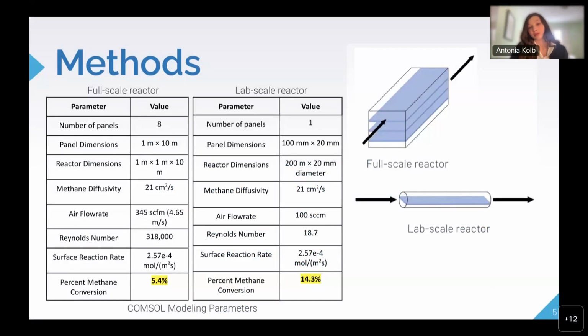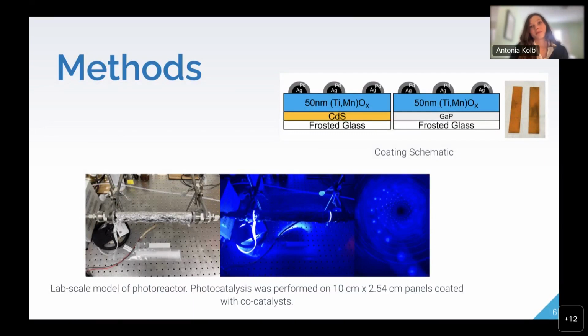This reactor would be placed in cow fields, oil fields, and other large sources of methane. The reactor was then built using LED lights as opposed to xenon lamps, which are typically used in photocatalysis, allowing the reactor to adequately scale in the real world due to its efficiency and affordability. Cadmium sulfide and gallium phosphide panels were then coated and functionalized with co-catalyst palladium silver titanium manganese oxide, as seen in the panel coating schematic here, and they were then tested in the photoreactor.